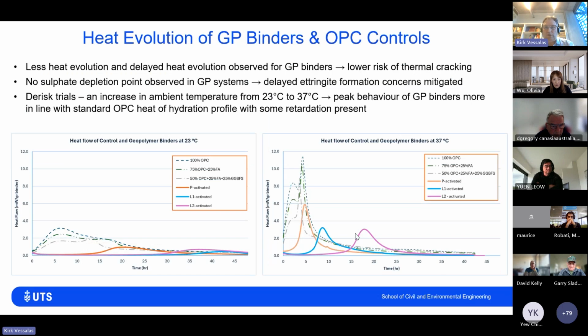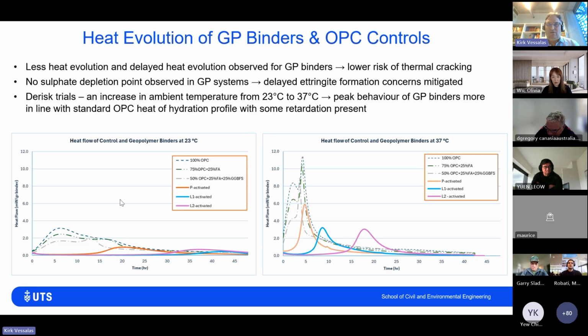So just sharing some of the results, and just bear with me as I explain what we have in front of us. We've got some isothermal calorimetry plots, which show the heat flow on the y-axis versus time. These give an idea of the hydration of the system. What we've done in this particular experiment is compare against conventional ordinary Portland cement, a research type binary blend, and also a commercial ternary blend that has both fly ash and ground granulated blast furnace slag.